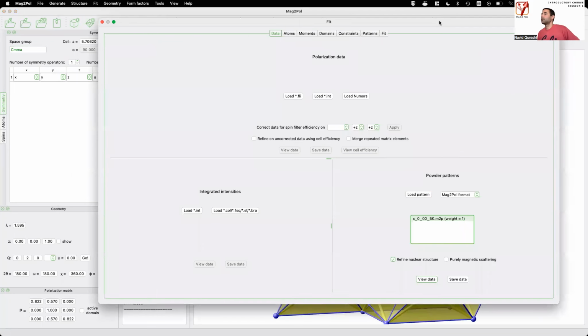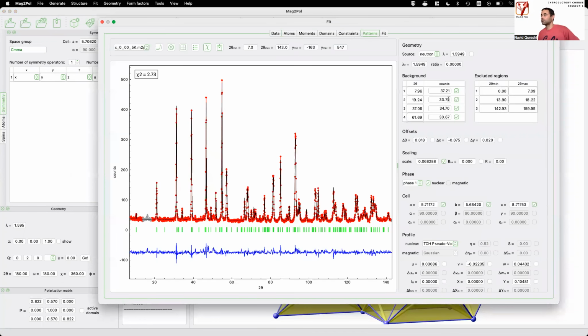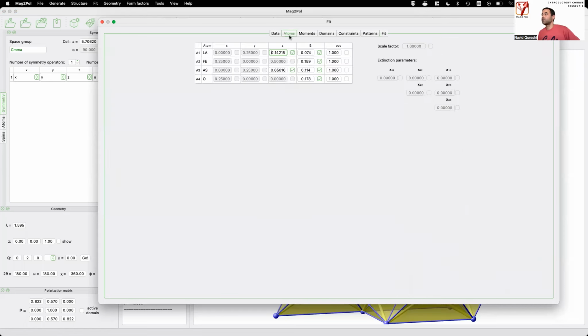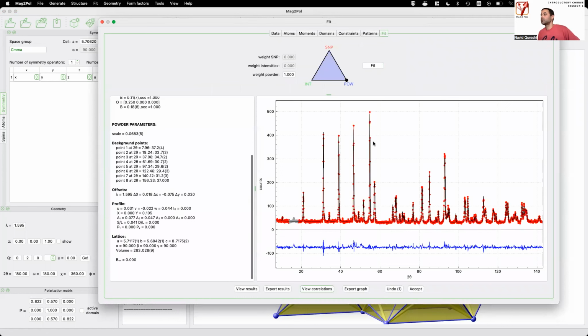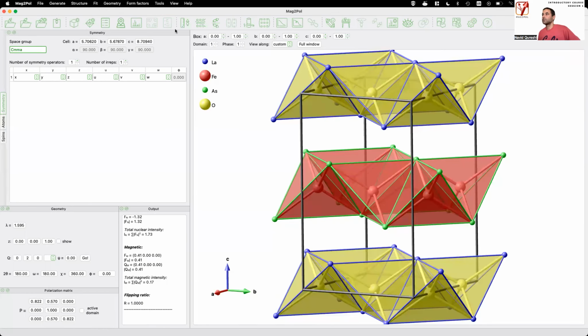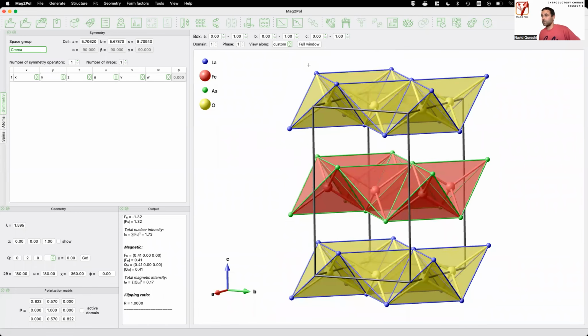And I have refined the 5K data using a linear interpolation of background points, a scale factor, and lattice constants. And I have refined the Z components of those positions which are free by symmetry, and an isotropic temperature factor for each of the atoms. So the fit looks good. I accept, I close. So this is nothing new because I have already done it before.